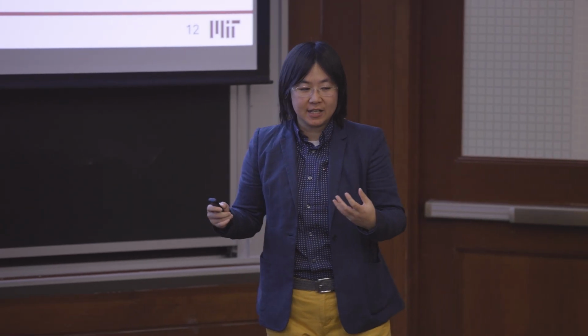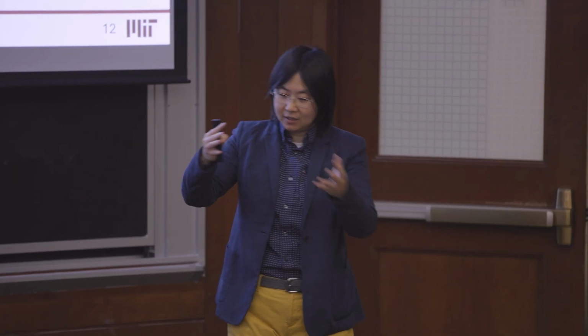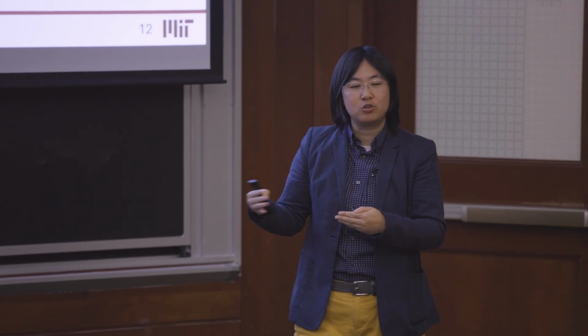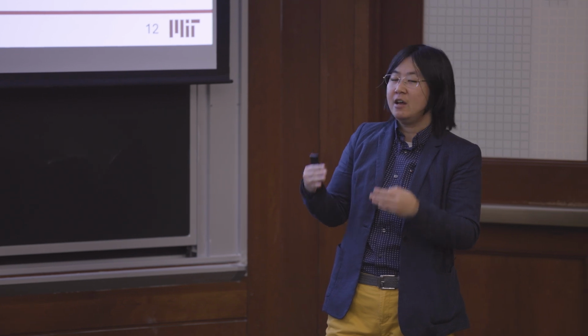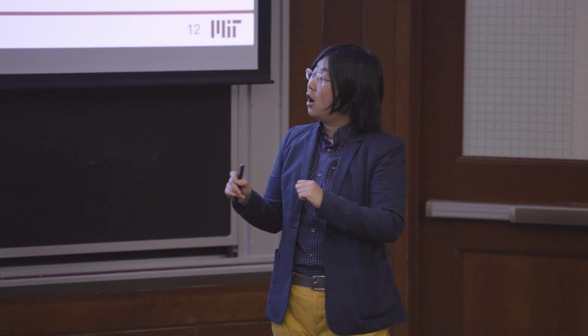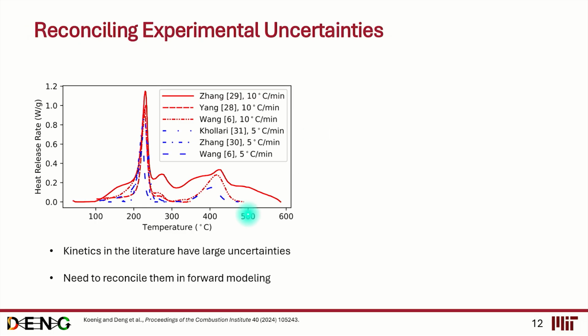We were very happy about it until we realized that across the literature, in addition to that single group that did a lot of experiments, there are also other people trying to repeat the same experiment following the same procedure. However, at their best, this is what all the experimental groups across the world can get. We see that generally we have the same trend. Some peaks happen at the same temperature, but not all the peaks, right? Sometimes you have 2 peaks, sometimes you have 3 peaks, and so on. They all claim to follow exactly the same procedure and use the same material.